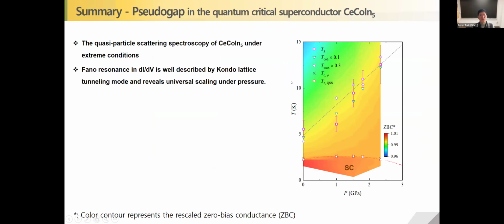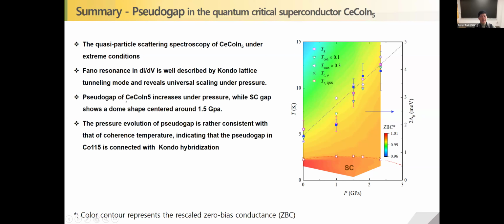Okay, so to summarize our work on the pseudogap feature in CeCoIn5 under pressure, we successfully performed quasi-particle scattering spectroscopy of CeCoIn5 under extreme conditions, and the Fano resonance is well described by the Kondo-lattice tunneling model, and this shows universal scaling under pressure. And the other thing is the pseudogap of CeCoIn5, as you can see here in the figure on the right panel, on the ordinate 2 delta is enhanced with increasing pressure, which is very different from the superconducting gap.